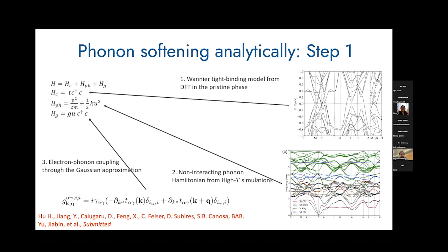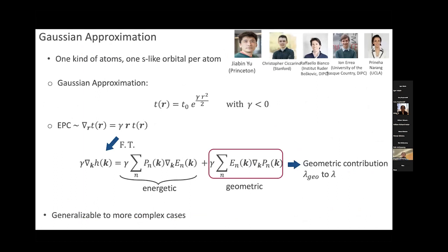orbitals. But what we're basically saying is that the phonon in charge of this CDW transition will couple the most strongly with the electron of the same symmetry that has the Wannier center where the Wannier center of the phonon is. And this is a principle that's based on some quantum geometry, which is a fancy way of quantifying Wannier centers. But it basically gives you, and you can justify it by assuming no angle dependence of your hoppings, which for s and pz orbitals can be correct, and some sort of Gaussian approximation. And then if you take the derivative of the hopping, it's exactly that coupling of two Wannier centers.